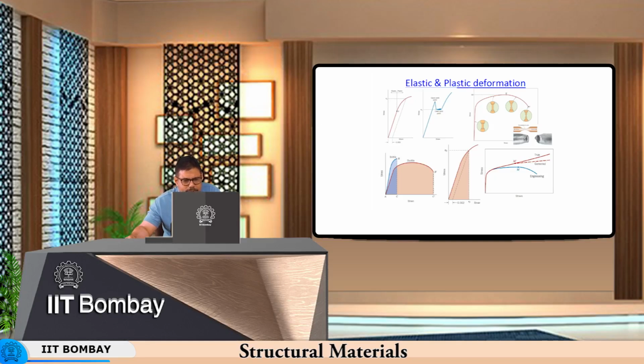Basically people give skin pass rolling or they give a small reduction in cold rolling to address this issue, so that this disappears. So, if you do get this kind of a phenomenon in the material, you need to give a very small 5% thickness reduction to that material, or 5% strain to that material by rolling, so that this